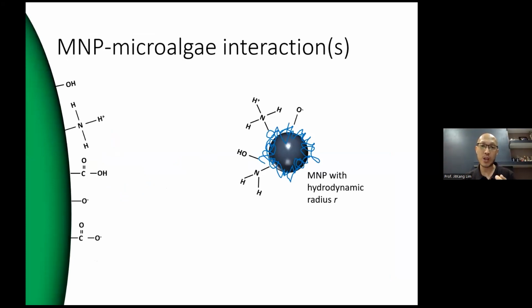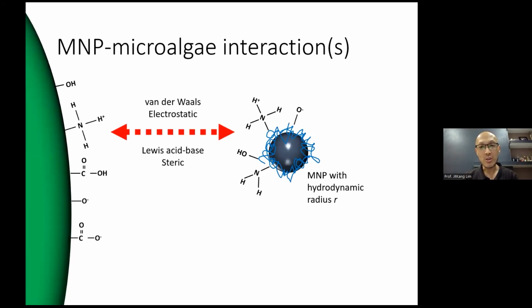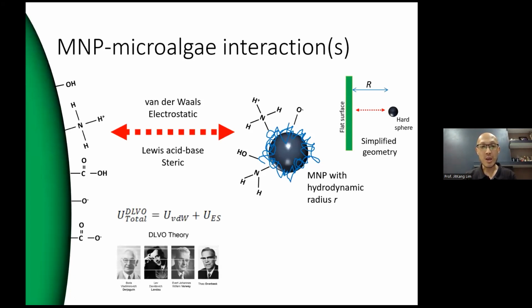So as long as we have a way to reverse such electrostatic repulsion, we could promote the particle attachment. The easiest way is to coat the particles with a molecule that carries a charge, and it has to be cationic, which is positively charged. So we decorated the particles with a polycation, polydiallyldimethylammonium, or PDDA, which is positively charged, and eventually we managed to promote the attachment of particles. We can also do interaction calculations, that is, calculate the interaction potentials between the particles and cell using simplified geometries, based on a classical theory developed by four scientists: Derjaguin, Landau, Verwey, and Overbeek. So it's based on DLVO theory.